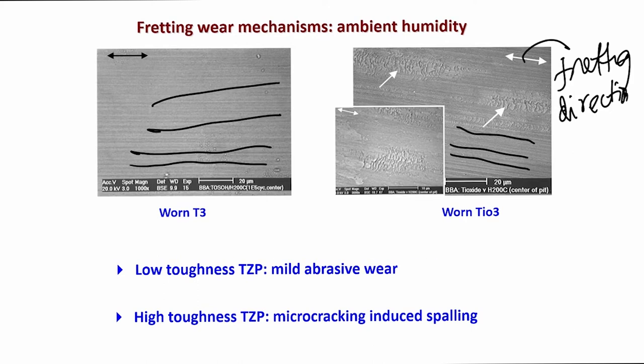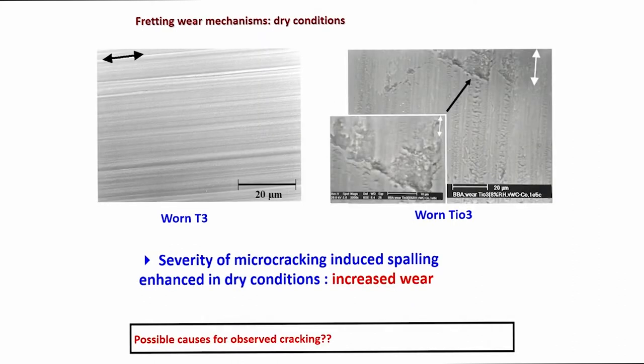Now, if you look very closely in this particular image, there are some micro cracks, and these micro cracks are aligned perpendicular to the sliding directions. And when these micro cracks are aligned perpendicular to the sliding directions, what will happen? These micro cracks can grow very fast, because in the perpendicular directions there is also a tensile stress field, and the tensile stress field can drive these cracks, and that can lead to measurable crack growth, and that can lead to micro cracking induced spalling. So, micro cracking induced spalling is the major culprit for the low wear resistance of high toughness tetragonal zirconia polycrystals.